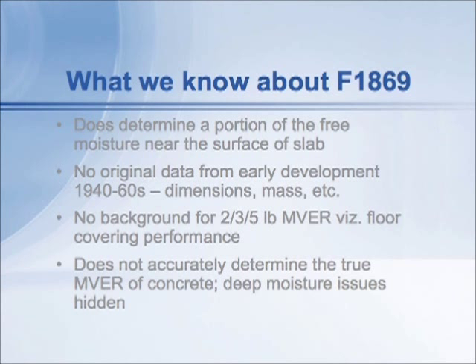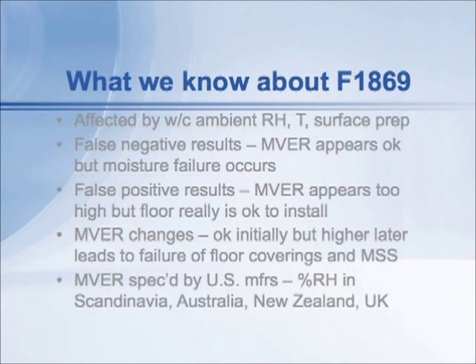We know that the test does not accurately determine the true moisture vapor emission rate as measured by ASTM standard test E96, and that deep moisture issues are actually hidden and not seen by this test method. We also know that the calcium chloride kit result is affected by water-cement ratio — the mix of the concrete actually has an effect on the results of the test. The ambient relative humidity and temperature also affect it: if you're measuring the calcium chloride value on a day that's cooler and drier you'll get a low result; on a warmer or damper day you'll get a higher result. You can get both false positive and false negative results.